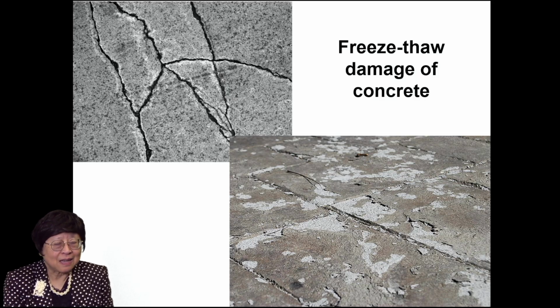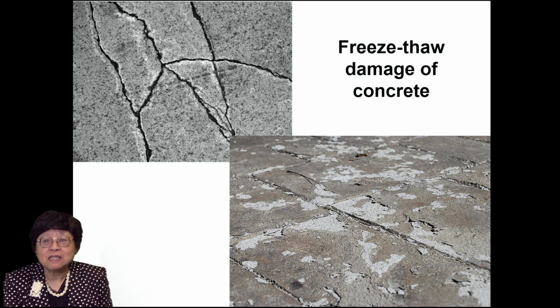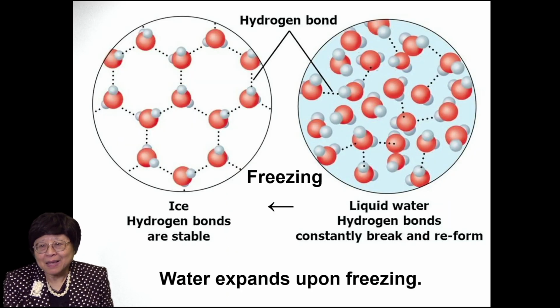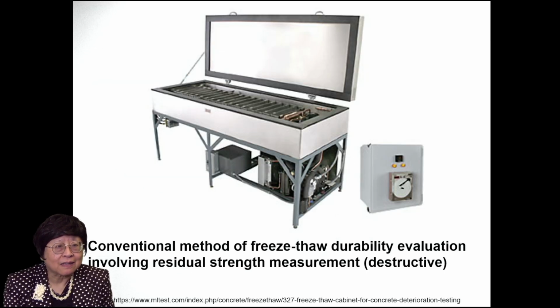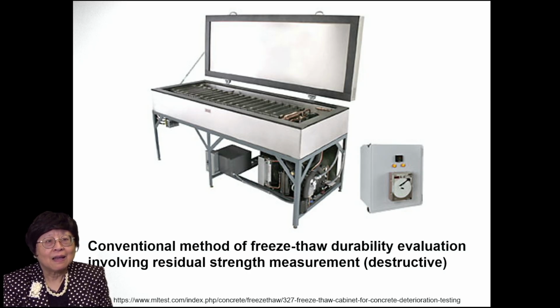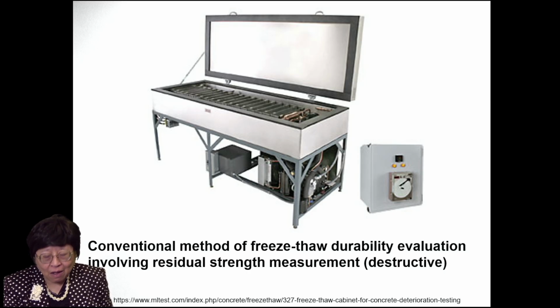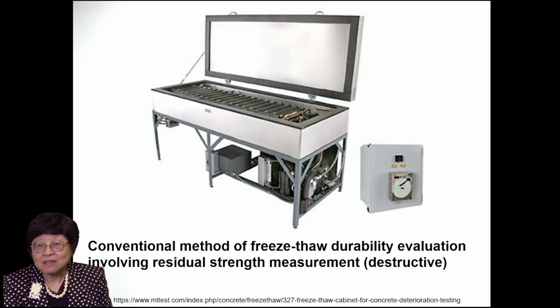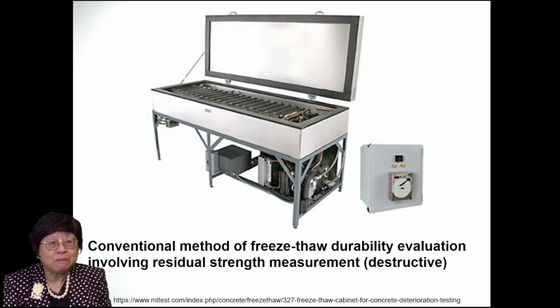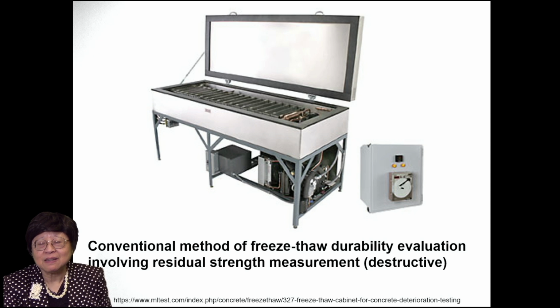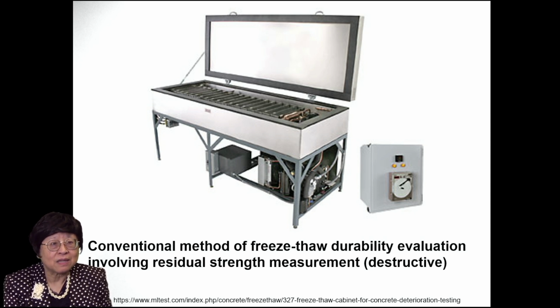Another cause of degradation of concrete structures is freeze-thaw damage. And that is because water expands upon freezing, and there's water inside the concrete. So if you have multiple cycles of heat, freezing and thawing, it's like fatigue, and the concrete can degrade. And conventionally, people study freeze-thaw degradation by having this chamber, which provides the temperature variation, and then studying the residual compressive strength after so many cycles.